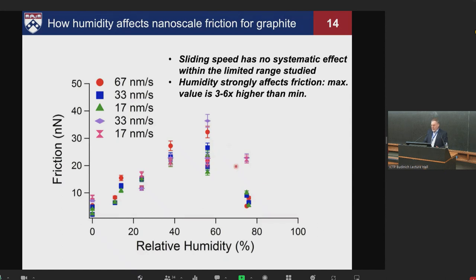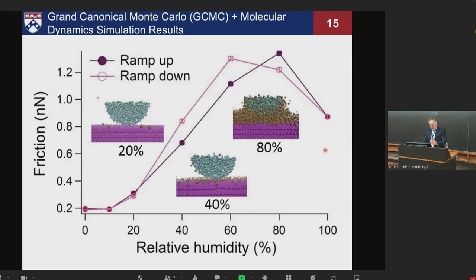So this tracks with what a full-blown theory for a tip on a surface would give for adhesion. And we thought, oh, okay, this is what we're seeing. A capillary forms, and then it floods, and friction goes up and down. Ashley's group did molecular dynamics simulations using a Grand Canonical Monte Carlo scheme where they could vary the partial pressure of the water, so tip, sample, and then water molecules that were simulated, and they also saw a maximum in the friction response for their simulations.